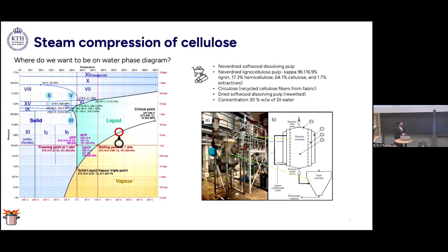The samples that we have used are never-dried softwood dissolving pulp and dried softwood dissolving pulp. Both of them have most of the hemicellulose and lignin removed, and because of that it's quite an inaccessible structure, and we wanted to see if steam is able to penetrate any of them. There's also a sample called Circulose, which is recycled fibers from fabric. And there is also a lignocellulose sample, which has roughly 17% lignin.